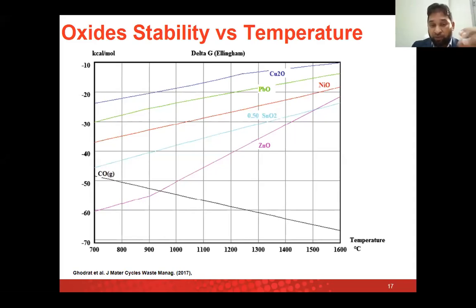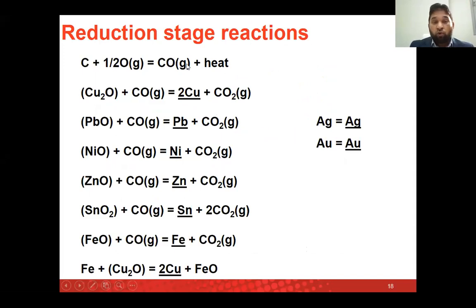So basically, from this diagram, we can predict that if we treat our copper that contains these oxides at a temperature above 1000 degrees centigrade, yes, we can reduce these oxides with the help of carbon monoxide to convert them back into metallic state. So in the copper smelting route, the first stage is reduction. The second stage is oxidation, and then we have the refining stages.